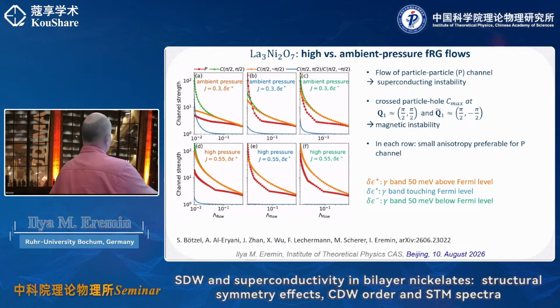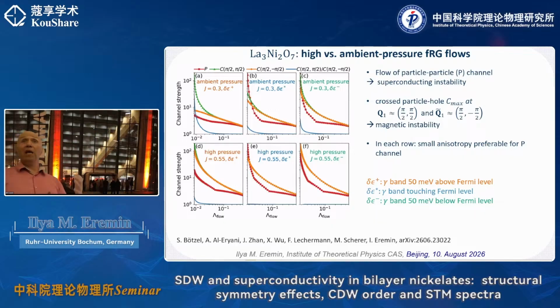Whereas if you look at the ambient pressure, you see from the very beginning that these two Q vectors behave very differently, because the structure has already chosen for you which wave vector it wants, because it will be just (0, π) and not (π, 0). And you also see that in the FRG flow, because these two different instabilities, the magnetic instabilities, behave very differently. So the anisotropy between π/2 and π/2 minus π/2 is increasing. So the magnetic one starts to dominate, and therefore superconductivity has no space to develop.